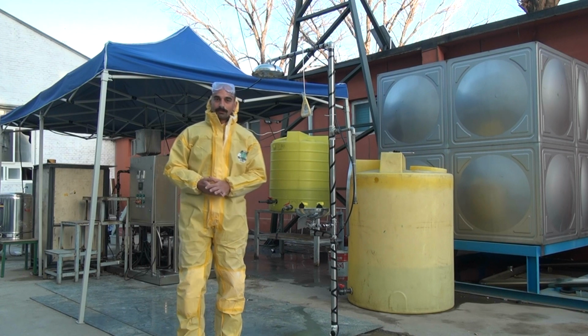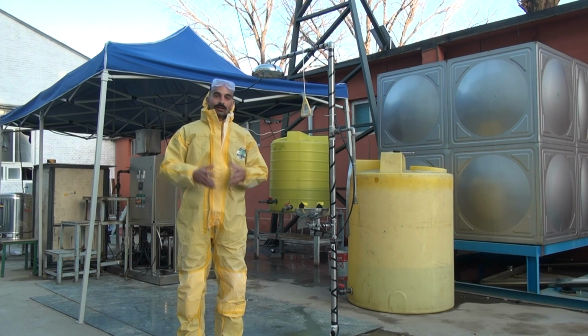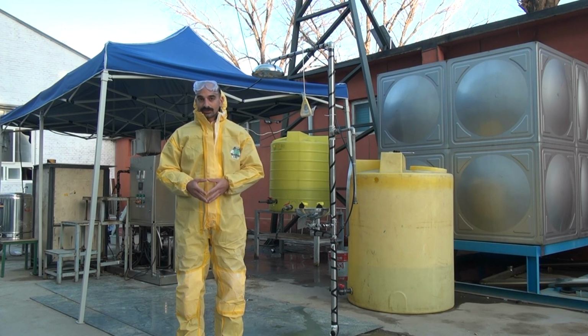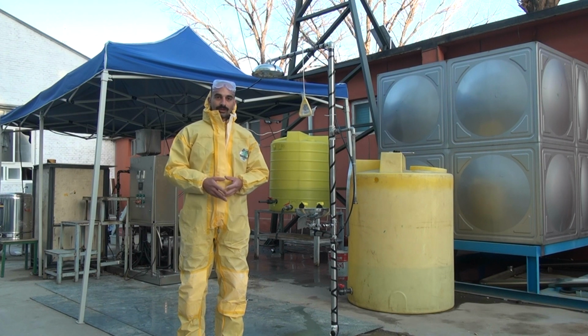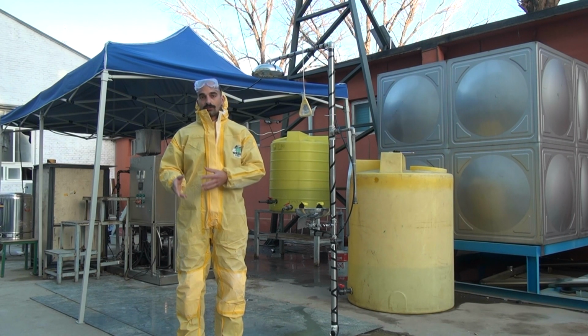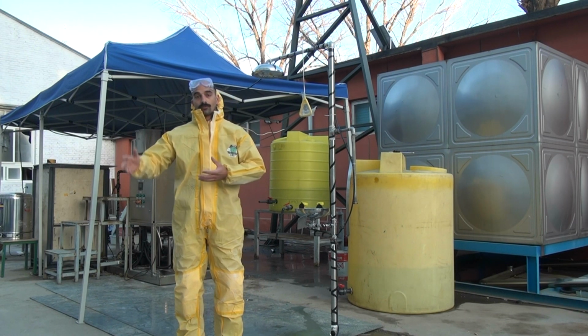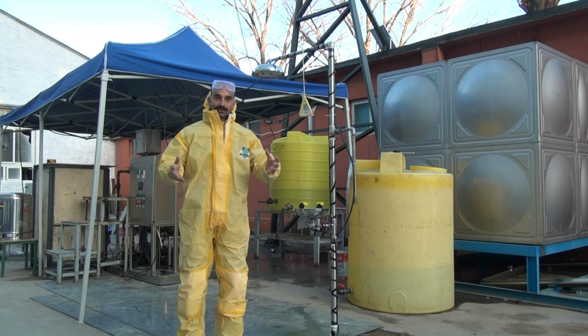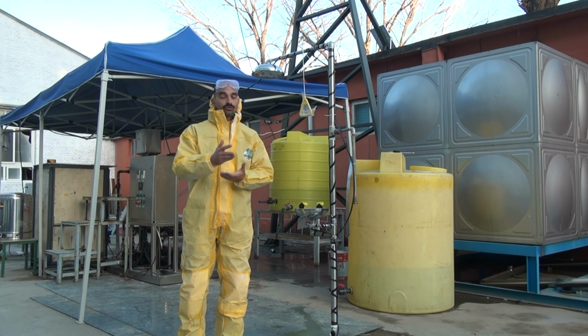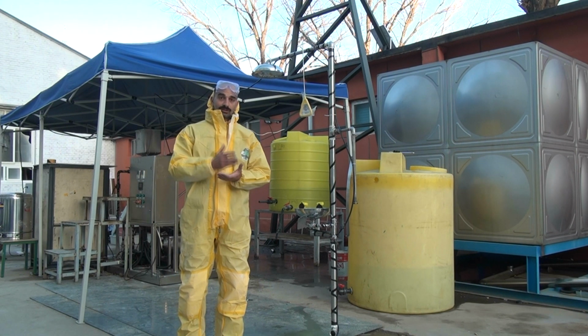And well, what was my PhD about? This video is supposed to tell you that. It is about an alternative route for the calcination of calcium carbonate, which you'll know is a carbon emitting process. It's conventionally made through thermal heating, and the PhD I did focused on a chemical calcination of calcium carbonate by using concentrated sodium hydroxide solutions, to convert calcium carbonate to calcium hydroxide, or portlandite, and sodium carbonate. So the trick is that while we calcinate calcium carbonate, we also trap just the process CO2 emissions whilst avoiding the combustion CO2 emissions.